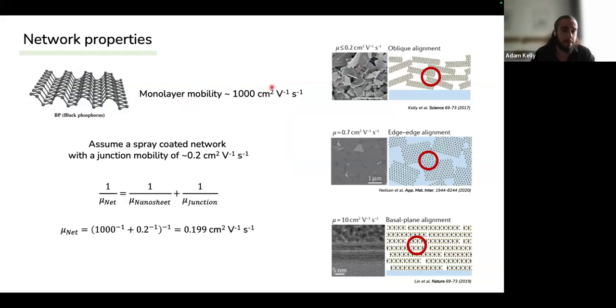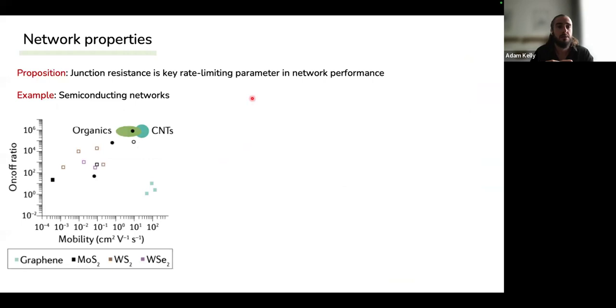Then by just applying Matthiessen's rule, what we find is that the mobility of your network will be completely dominated by the mobility of the junctions. So it doesn't matter how good your material is. If the junction resistance is extremely high, you're never going to be able to hit these material properties themselves. So the proposition here is that the junction resistance is the key rate limiting performance parameter for your network.